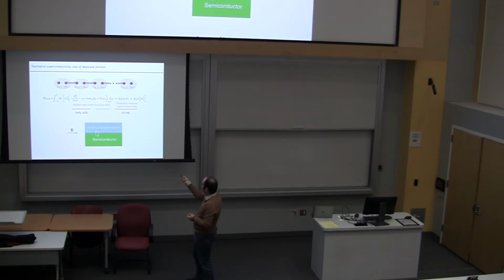If not, then I have it broken in here. So it's based on this Kitaev chain. It's in one dimension, right? You need this chain to have Rashba spin orbit interaction, and we know that in indium arsenide, indium antimonide, bismuth selenide. There are lots of materials with the strongest spin orbit interaction.